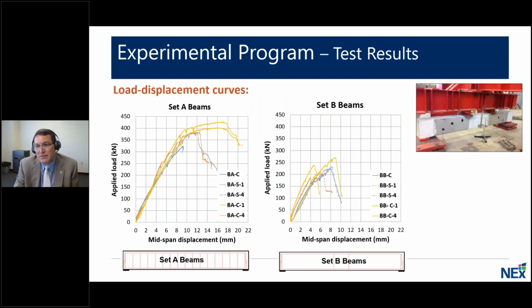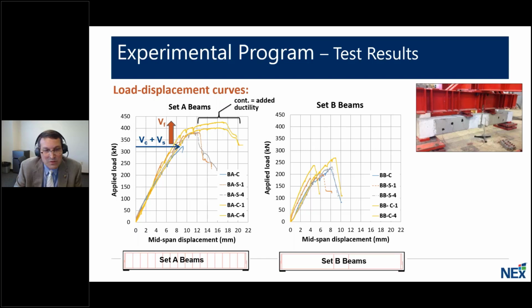So now let's examine the results in shear. First, for set A, as shown at the bottom with internal steel, we can compare the capacity of the beam with the steel stirrups and the concrete. Again, the blue line is the control specimens. And we can see that all of the beams had an increase in shear capacity due to the strengthening of the system. However, there was a significant difference between continuous FRCM shear reinforcement versus strips. The continuous had a greater ductility added versus the strip reinforcement that was used. So you can see the benefit of using continuous shear reinforcement of FRCM.